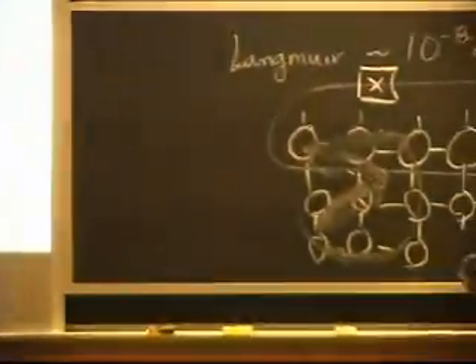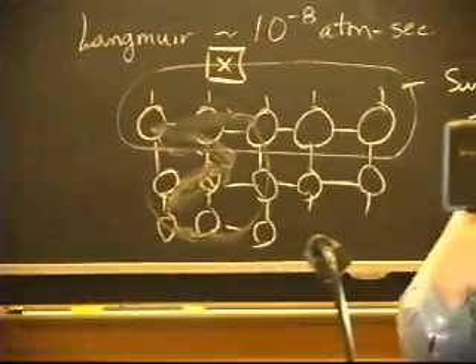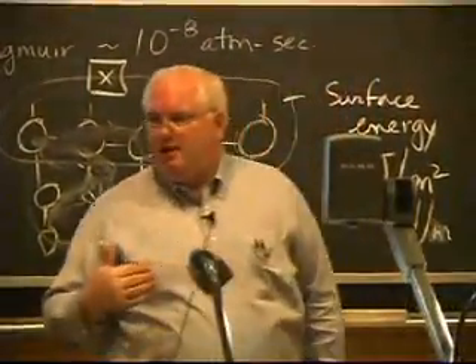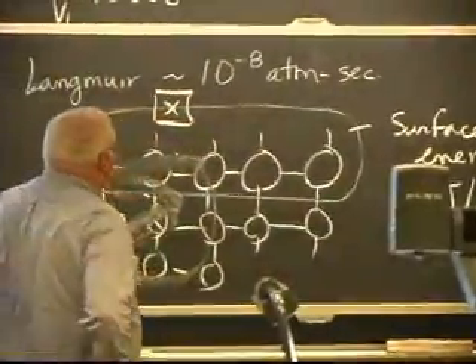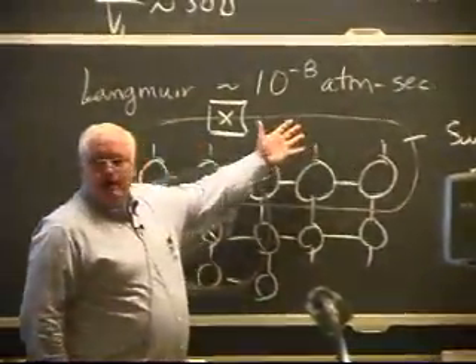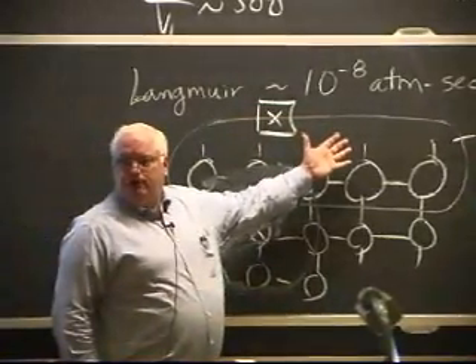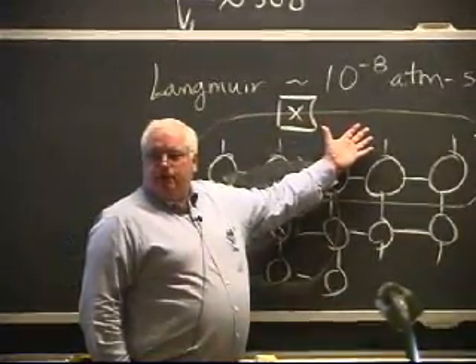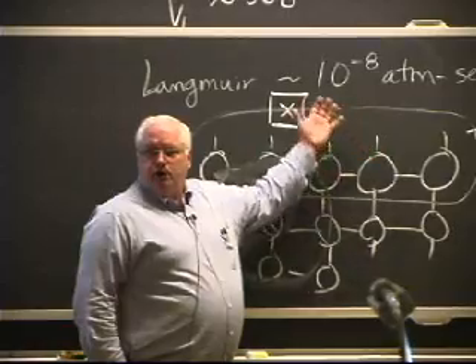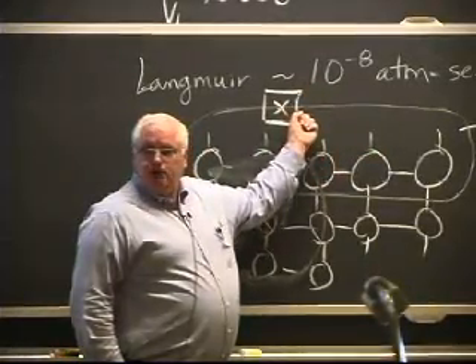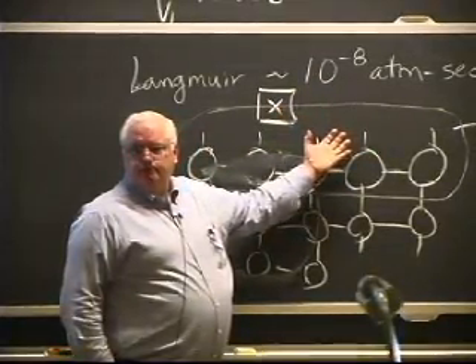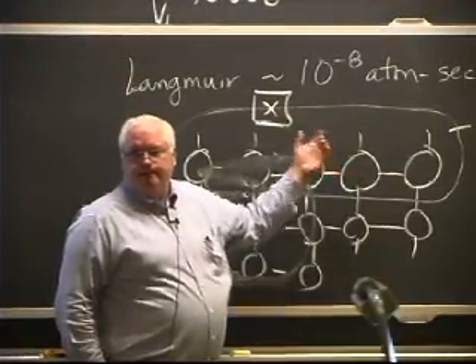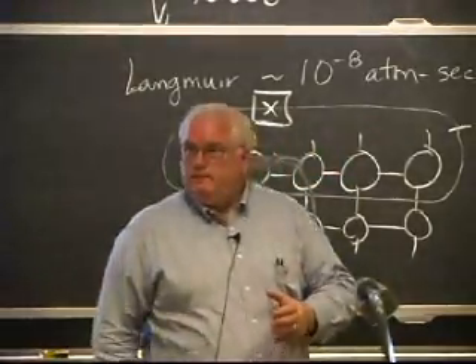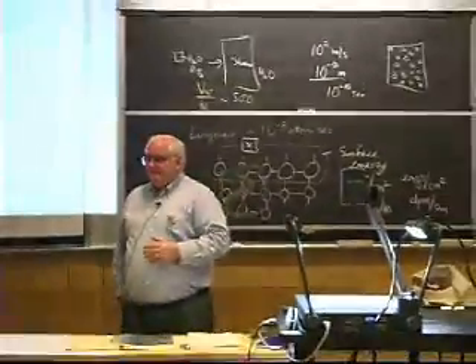And that means that metals are going to want to bond strongly if you can get them clean, but it also means metals are going to be very easy to contaminate, and they're going to be hard to get clean, because if I create a new metal surface, it has 3 times as much surface energy that it wants to get some contaminant on there to lower its energy. Because when the contaminant comes to the surface, it's bonded to the surface and it lowers the energy of the system. It's a spontaneous process, right? So that's one of the problems.